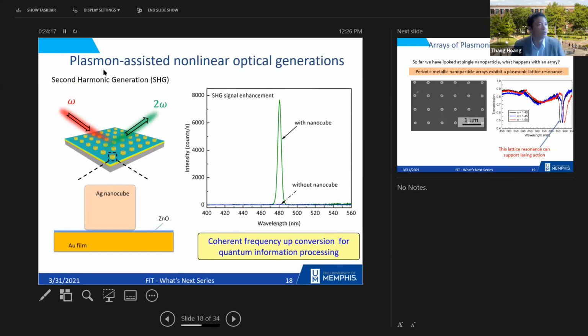For example, in this case, I saw plasmon-assisted nonlinear optical generation. We have an array of nanocubes, and in this case, we don't need the quantum dot. We can hit the laser with the frequency of omega. This surface has an array of nanocubes on top of a gold film, and in between, a very thin, about 3 nanometer zinc oxide layer. Then we observe that the second harmonic generation from such a surface is much stronger compared to the case where there's no nanocube, okay? We see up to a 10,000 times enhancement in the second harmonic generation.